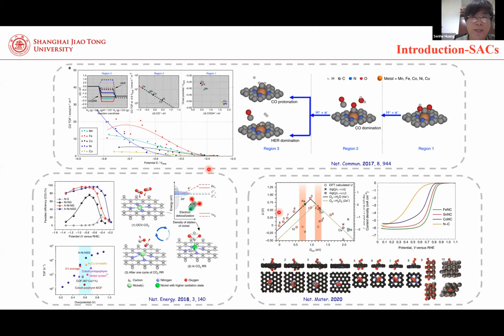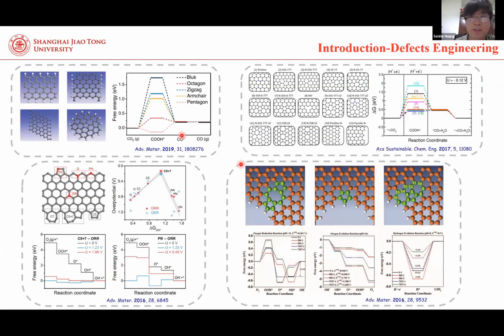So in recent years, single atom catalysts have attracted much interest. In the single atom catalyst, the metal can be atomically dispersed in the catalyst support. By combining the advantages of the metal center and the catalyst support, the single atom catalyst can exhibit high efficiency, high selectivity, and structural tunability. Especially the single atom catalyst with metal-nitrogen-4 sites, like this one, is the most representative single atom catalyst. A high specific surface area of the porous carbon support can guarantee the efficient accessibility of active sites during catalysis.